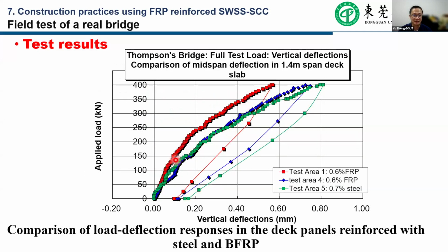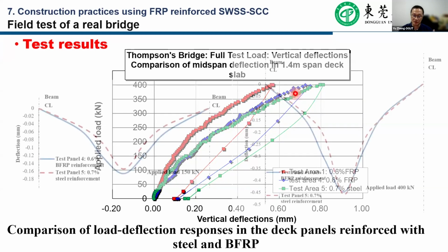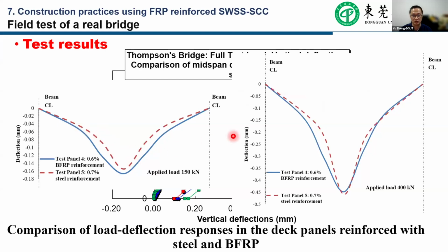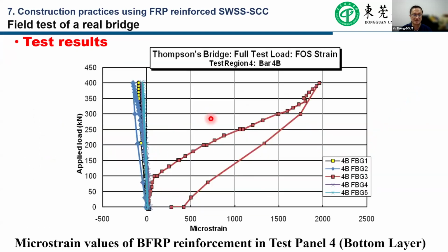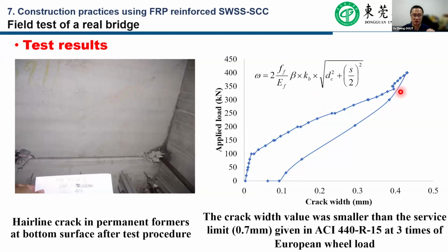But this is the most interesting: we can compare the load and deflection of the FRP reinforced bridge deck and the steel reinforced bridge deck. Even though the reinforcement ratio is similar, the FRP reinforced bridge deck slabs show similar behavior to the steel reinforced one due to the existence of the arching action. The total deformation behavior is also very similar, and the strain is very small in this test, and the crack width is also very small too.